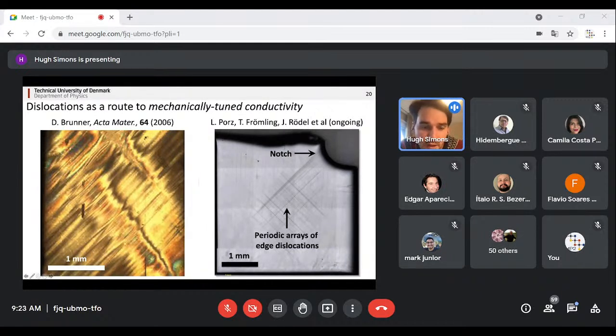And they had done some visible light microscopy and seen these dramatic patterns forming due to the dislocations. And they were able to make these notch-type specimens, which created these periodic arrays of edge dislocations. And the idea was that essentially these dislocations should have different electrical conductivity through them compared to the bulk. So the idea was that maybe they can have some kind of tunable electronic properties of their material by maintaining or by perturbing the distance between these dislocations. But the problem is they had really no way to understand what the dislocations were doing in the bulk of their crystals.